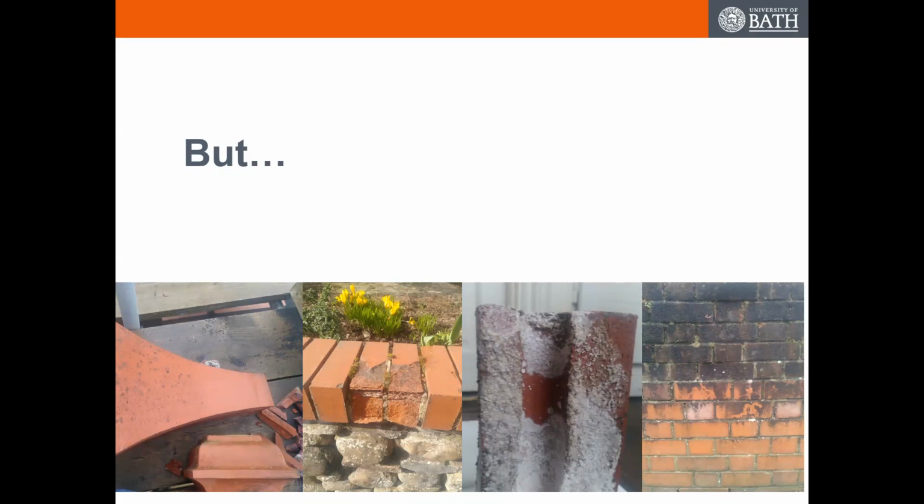So it's exactly the same exposure, exactly the same water exposure, exactly the same sunlight, and exactly the same species. It's only the difference between the bricks that is causing them to grow there or not. And that's not necessarily the porosity, it's also the surface roughness, which is causing the water to spread, giving the algae basically something to grip onto, at quite rough scales. I think you'd call them gritted bricks or possibly water struck, depending on where you're at. So I'm just setting up a few caveats before we start the rest of the talk.